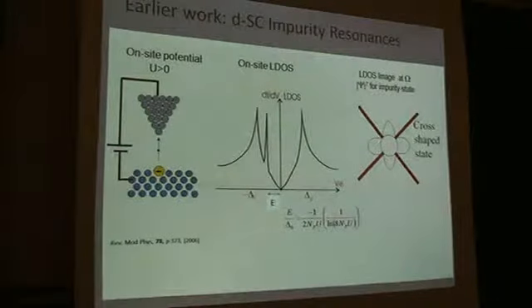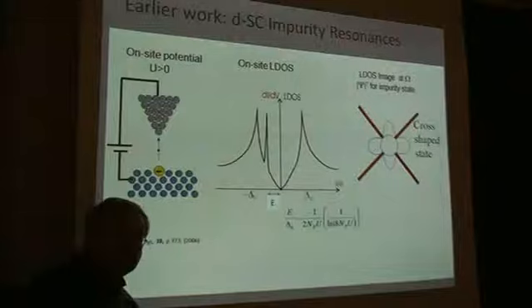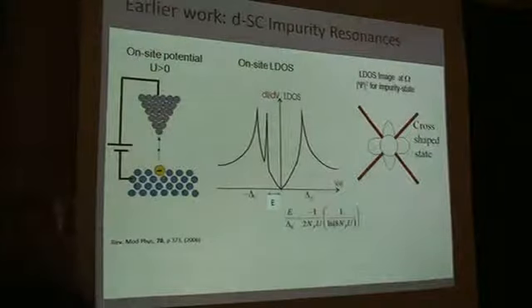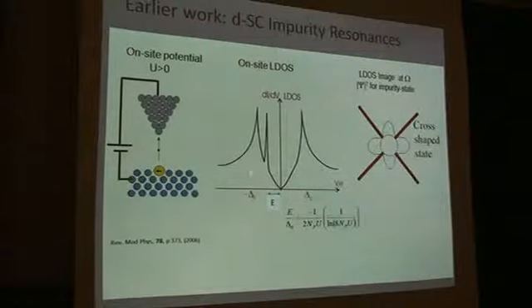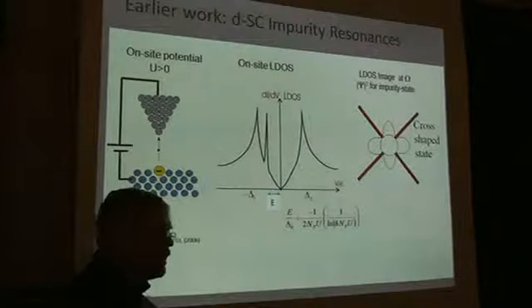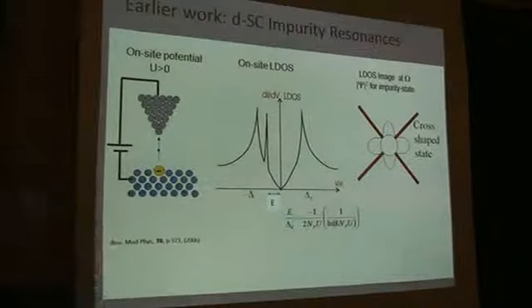Number one is that what you start seeing is actually these coherent peaks coming from the D-wave gap with the field-in states, due to this nodal gap structure. There is one additional resonance that comes in. It's already, if you want, a harbinger of death of the superconductor, because if you keep doing it, you will have more and more states pulling inside, and they will fill up the gap, and the superconductor becomes normal. In a way, every course of Gorkov discussion about the gapless superconductor is a kind of pre-tipping state of the superconductor where all these impurity resonances fill up the gap and make it gapless.